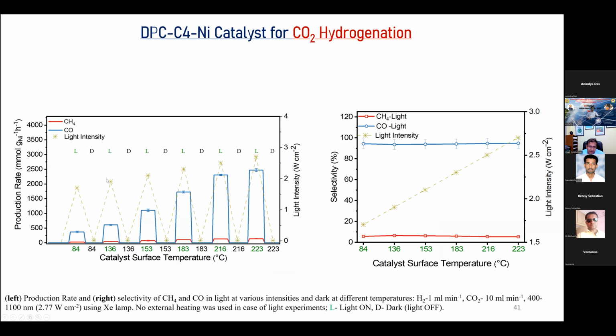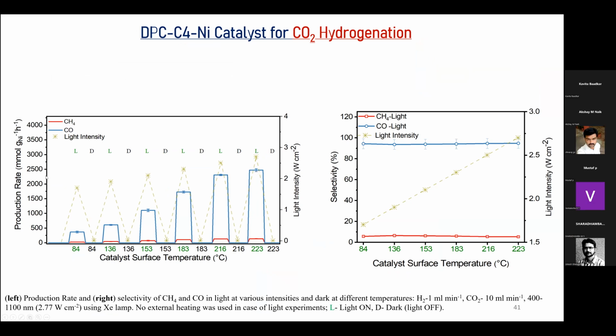As soon as we switch on the light and kept increasing the intensity, we clearly observe extremely good yield. At around 2.2 or 2.5 watts per centimeter squared light intensity, the yield is around 2,200 millimoles per gram. See the number, millimole per gram. The number I showed you previously was 1.5 micromoles per gram, which suddenly jumps into millimoles, around 2000. So you can see a dramatic change in catalytic activity simply by tuning the catalyst design.